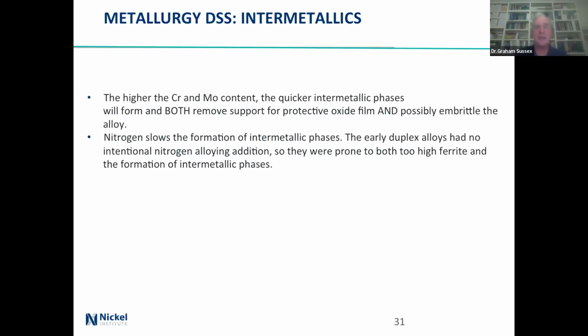And looking at intermetallics, the higher the chrome and moly, the quicker they're going to actually form. And they're going to remove support of the protective oxide film that's on the surface, and quite possibly embrittle, because when they come out and you get down to room temperature, they will just embrittle and crack. They also take away the protective oxide, so then you may actually just wind up with corrosion.